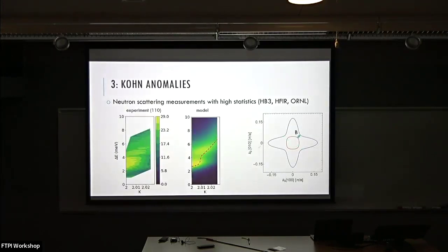But it's quite nice that we also see these others, and it should be helpful to actually discriminate between one phonon and two phonon, because these interactions also depend on Q. The large coupling is actually strongest here. It's very weak here. Of course, this interband can be caused by two phonons instead of one phonon. So there's a lot to do with these data. But the fact that this is observed is very nice.